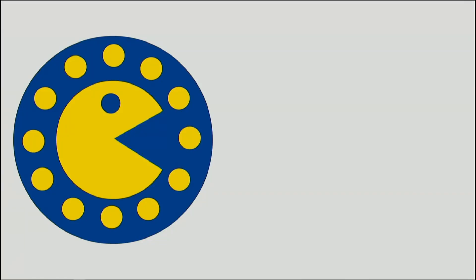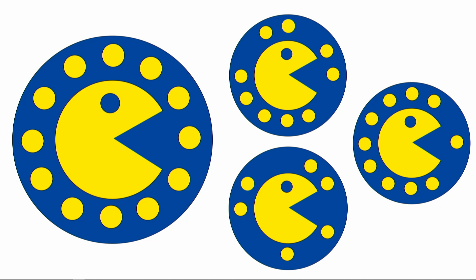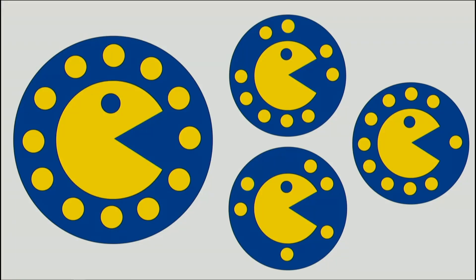Like this one. This was the result of a collaboration with a fellow named Stephen Nightingale. We can draw just about any picture we want in the cross-section of the fiber, which means we can selectively turn these dots on or off. And with enough dots, you can form millions of unique, distinct dot patterns in the cross-section of the fiber. That makes the cross-section a two-dimensional barcode that can be read by a scanner that's really just a microscopic version of the scanner you use at the grocery store. The Pac-Man in the center tells the scanner where 12 o'clock is, so the dot patterns aren't ambiguous. And that same dot pattern runs through the entire length of the fiber. So if we slice the fiber into 10-micron disks, the result is a very fine micropowder with that same unique identifying dot pattern on every single particle.